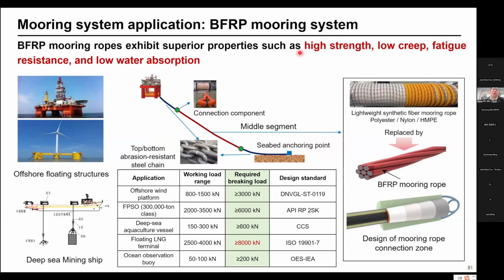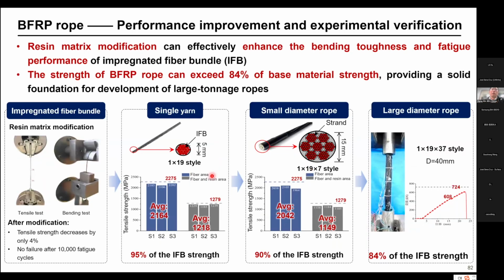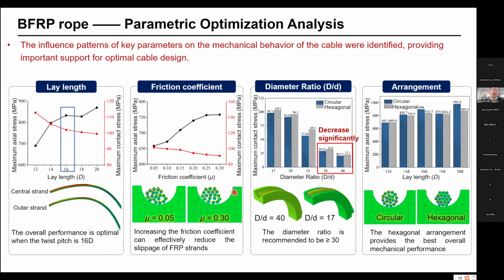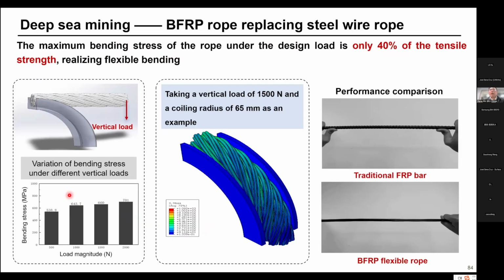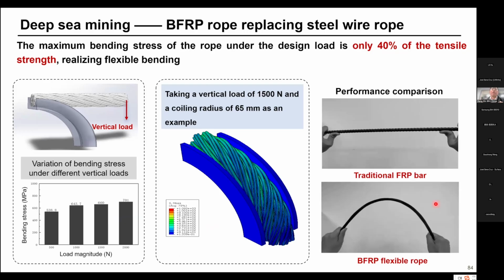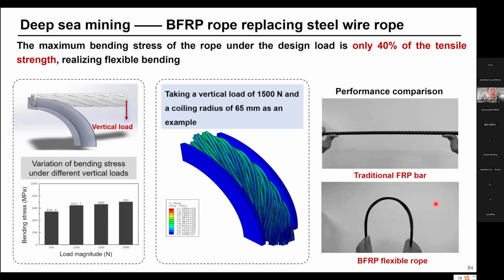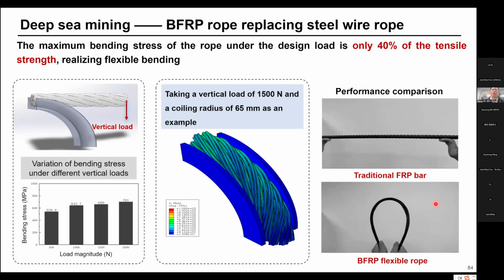And finally, it is for the mooring system. So the mooring system is not only used for those platforms, but also for the mining ship, this kind of structure. Yes, so it can provide very good durability, and also we can make it so it can be bent. This is very important. So typical FRP cannot be bent very well. So we need to modify the resin. We need to make it twisted, and also we do some optimization about the friction, about the diameter, about the twisted angle. So finally, we can make FRP easily bent, make it a flexible rope. It's not a fiber rope, it's an FRP rope. So the durability, the wearing ability can be greatly enhanced.